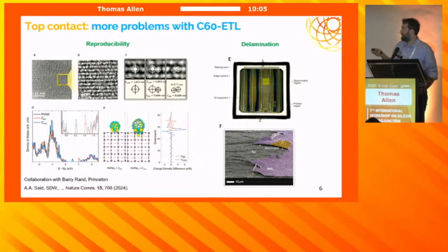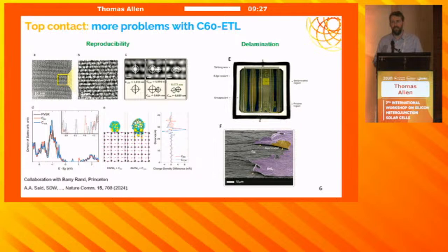And then a lot of chemical characterizations of the C60 showing that these fullerenes agglomerate, forming, for example, a C120. And this introduces defects not only within the C60 itself, but also within the film. It limits the mobility, and you see a steady decrease in performance of the solar cells that I haven't shown here, but you can see in the paper. You can get rid of this effect by using an ultra-pure C60, and so this is Barry Rand's contribution from Princeton to this paper. So using that very high purity C60, you can do repeated evaporations and repeated thermal cyclings without getting this detrimental effect, but you have to use the pure stuff.